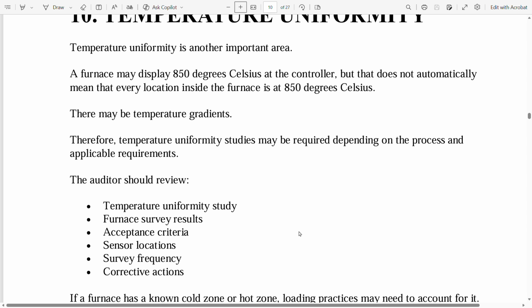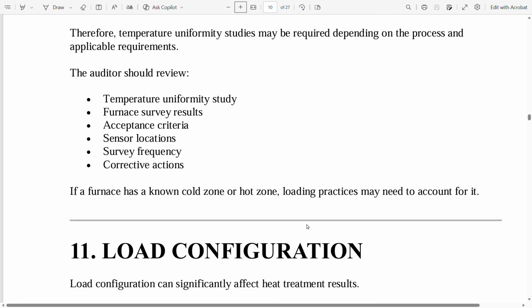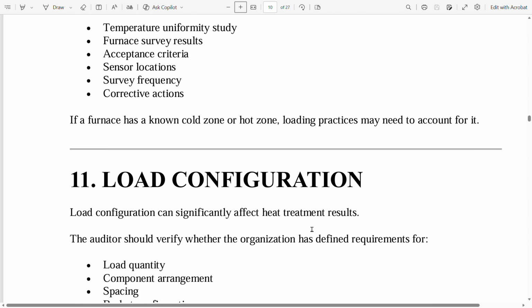Therefore, temperature uniformity studies may be required depending on the process and applicable requirements. The auditor should review temperature uniformity study, furnace survey results, acceptance criteria, sensor locations, survey frequency, corrective actions. If a furnace has a cold zone or hot zone, loading practices may need to account for it.